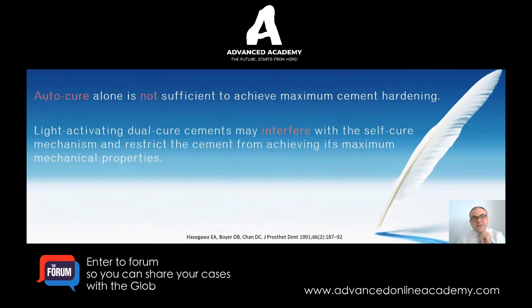Now, if you ever thought about this: if you have a dual cure cement and you placed your crown very quickly, cleaned the margins, and then cured it with your light, the light curing process can paralyze the chemical component of the cement from working. We're currently working on a project right now with one of our residents, Dr. Bashair, from Saudi. One of her projects was, does the curing time affect the bond strength and the properties of the cement? So we cured it immediately, then after 2 minutes, after 5 minutes, and then after 10 minutes. We delayed the curing process.